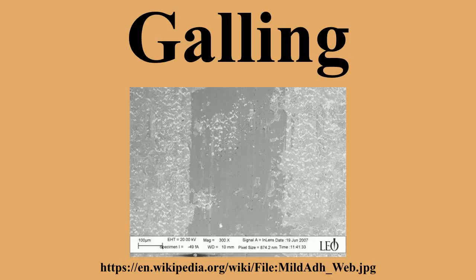This leads to greater adhesion between the surfaces, which initiates material transfer, galling build-up, lump growth, and creation of protrusions above the original surface. If the lump grows to a height of several micrometers, it may penetrate the opposing surface oxide layer and cause damage to the underlying material. Damage in the bulk material is a prerequisite for plastic flow that is found in the deformed volume which surrounds the lump. The geometry and speed of the lump defines how the flowing material will be transported, accelerated, and decelerated